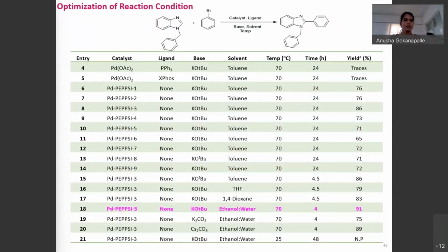Optimization of reaction conditions. We have taken N-benzyl substituted benzimidazole molecule and phenyl bromide as a model reaction. First, we started the reaction with palladium acetate as catalyst and triphenylphosphine ligand, but at 70 degrees centigrade we observed only a trace amount of C2 aryl substituted benzimidazole. Next, we switched to the reaction with palladium PEPPSI catalyst, and we observed moderate yield, that is 76 percent of C2 aryl substituted product.